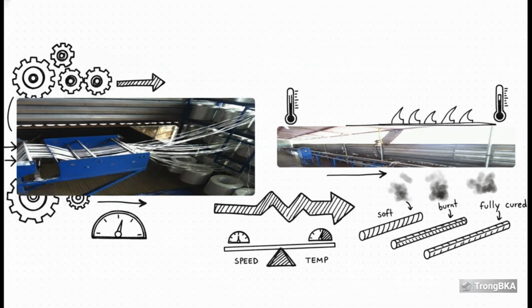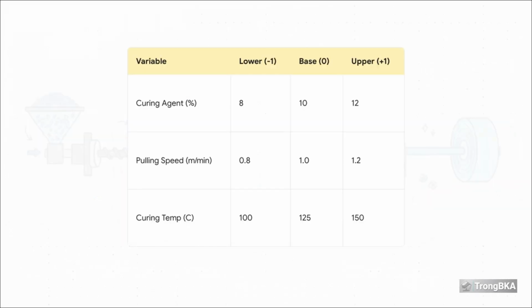If your temperature in that tube is too high, the epoxy can actually burn, but too low, and the rebar comes out soft and basically useless. To find the absolute perfect recipe, engineers rely on a level 2 orthogonal experimental matrix. They meticulously test different combinations of 3 main variables: the percentage of curing agent, the pulling speed, and the curing temperature. By testing the lower levels against the upper levels, they can mathematically pinpoint the exact manufacturing sweet spot that results in the maximum ultimate tensile stress for the final product.